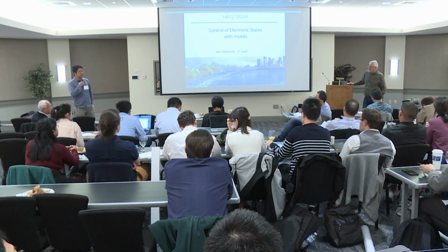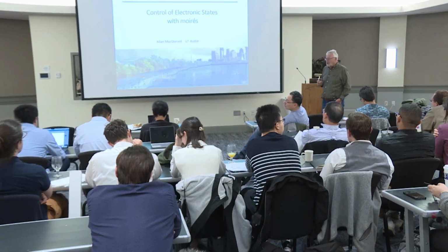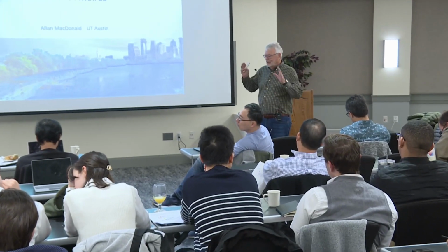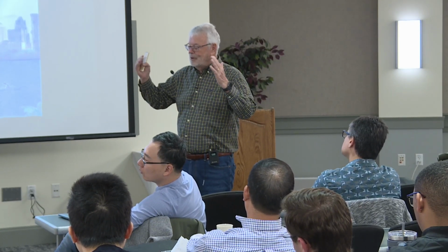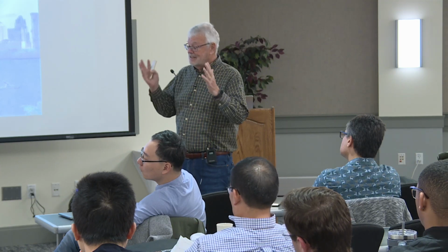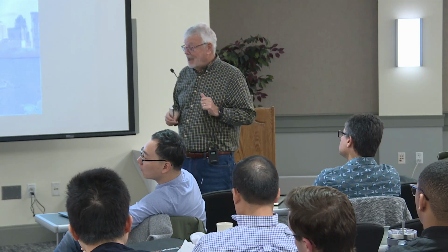I think the key thing is that all of the low energy states, and I didn't define those words, it means over an energy range that's comparable to the interlayer coupling terms in the Hamiltonian, or the stacking dependence of the Hamiltonian, they have to be in a small region of momentum space that doesn't change with stacking. So let's say for niobium diselenide, none of this works.